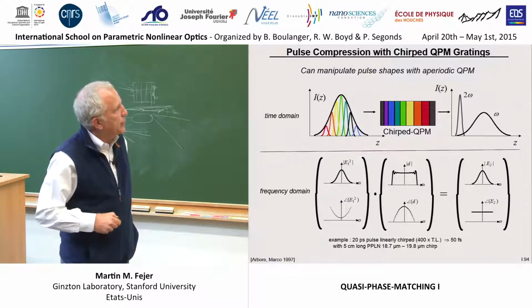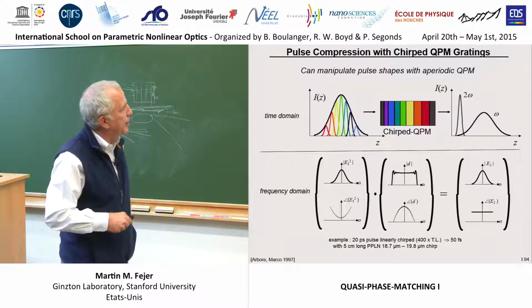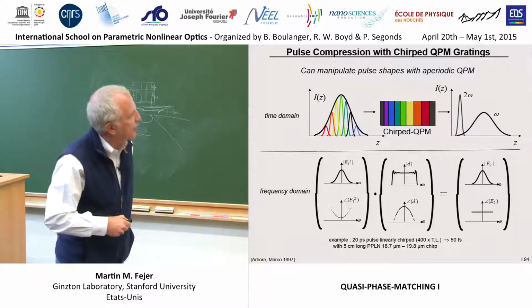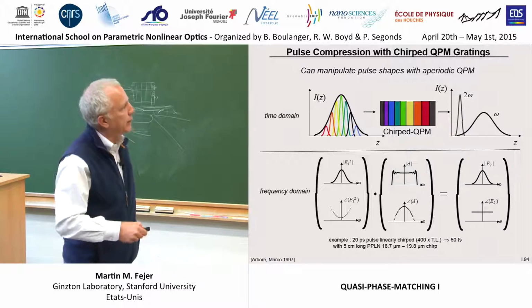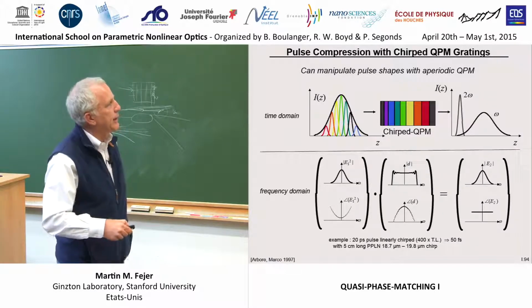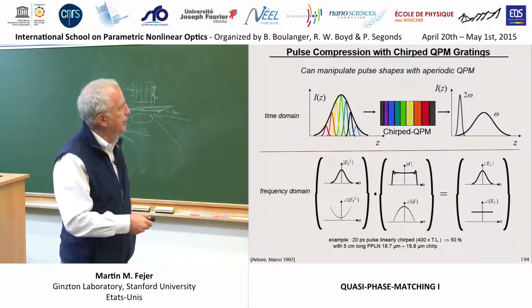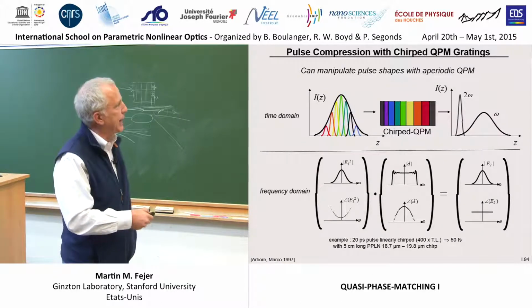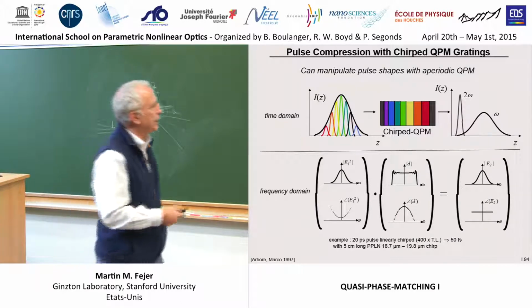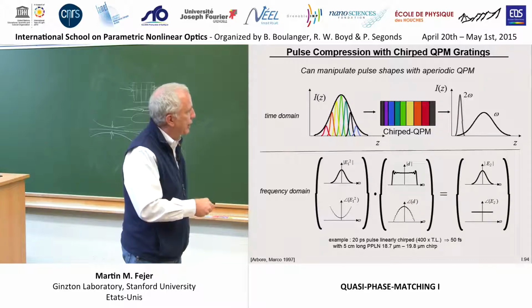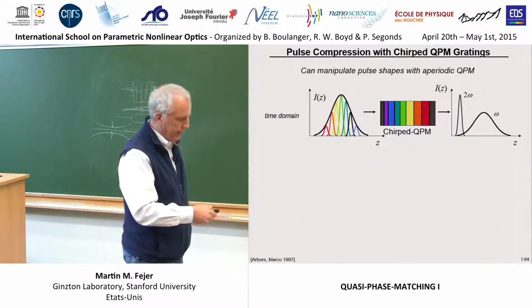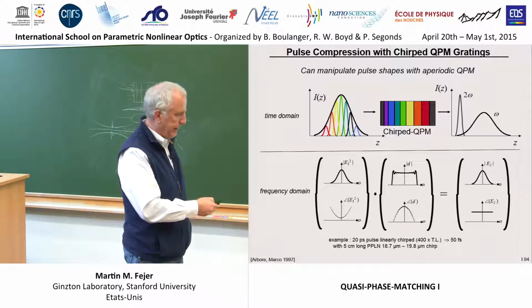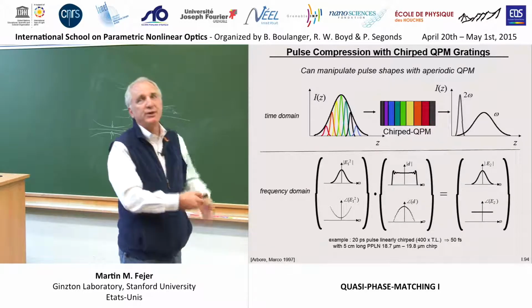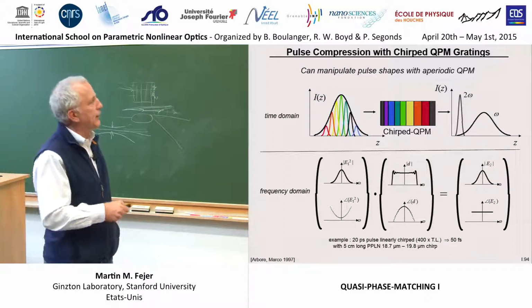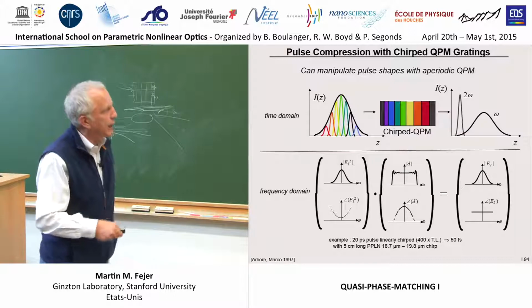And so if we choose the chirp to be large enough that the bandwidth of this transfer function exceeds the bandwidth of the fundamental, then all of the Fourier components in this pump pulse will convert with equal efficiency. The product of this wide bandwidth and that narrower pulse is that pulse. So we preserve all the spectral components. And if this phase curvature is equal and opposite to that phase curvature, then the sum of those, the input times the transfer function, is just flat phase. It's a compressed pulse. So whether you look at this thing in the time domain or the frequency domain, you again get the same answer.